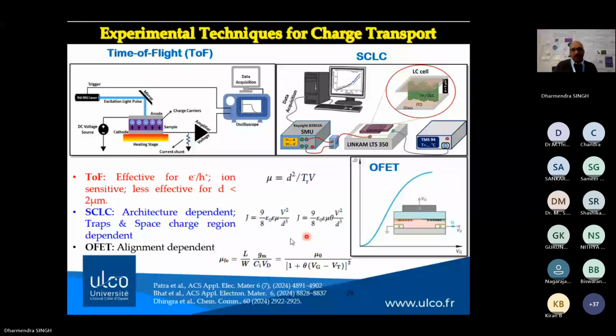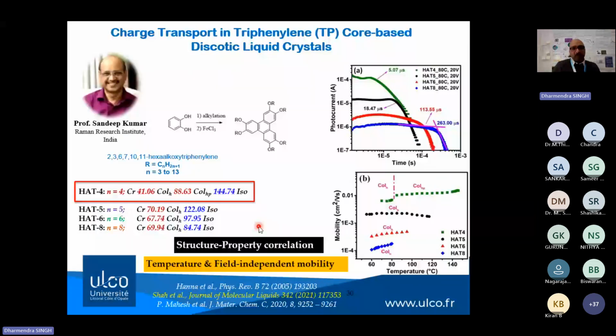semiconducting materials. In fact, we then continued our research exploring different chemical systems, which were organic materials. This first system was developed by Professor Sandeep Kumar. Here you can see a triphenylene core-based disc-like molecule. This is called the central core unit, made by the triphenylene moiety. And here is the functional group, the alkyl chain. R is the alkyl chain, where R is CnH2n+1, and you can change n from 3 to 13.